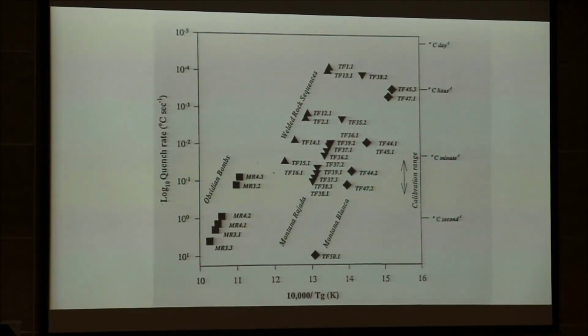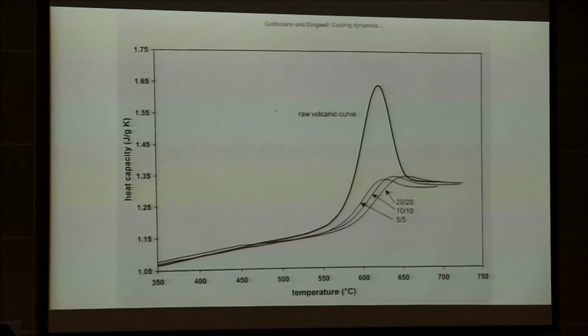So we got samples which cooled at rates of 10 to the 1 to 10 to the minus 4, 5 log units variation of cooling rate for one chemistry, one volcanic system, one volcanic phenomenon. Okay? It means that there are widely different fates which are experienced by these volcanic glasses. This is the most extremely slowly cooled glass we've ever seen. It's from Mayor Island in New Zealand. It's a glass which won't crystallize no matter what you do to it. It's a very special chemistry.